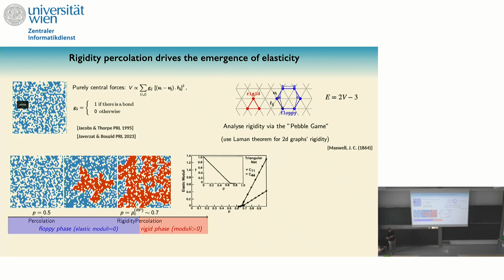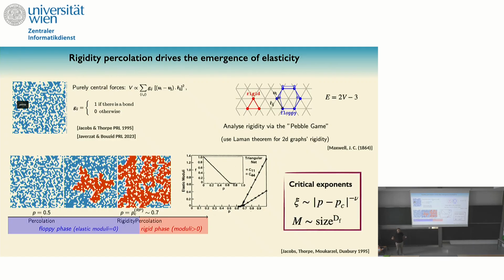So you can use your model to compute the elastic modulus. And here, what you see, if you compute the bulk or the shear modulus, is that up to this critical volume fraction your modulus is 0. Then at the critical volume fraction where the system percolates, you have a finite modulus. So there is a transition. It's a second order phase transition that emerges when all those clusters start to merge together, and they have enough constraints, or more constraints than degrees of freedom, in order to be rigid. And this transition is, like all second order phase transitions, characterized by critical exponents.